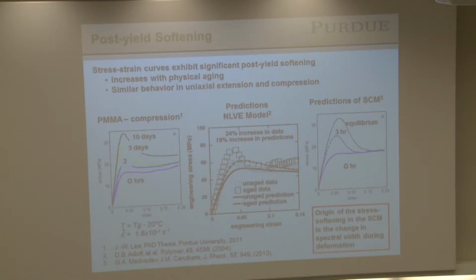Okay? Does it work? Well, qualitatively, it's working really pretty nice. This is polymethyl methacrylate. It shows the stress-strain curve in compression, and what we see are these curves here. We see this overshoot peak, this post-yield softening, and it changes with how long we age it in the glassy state. So this changes with time.